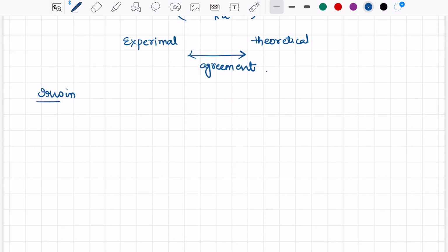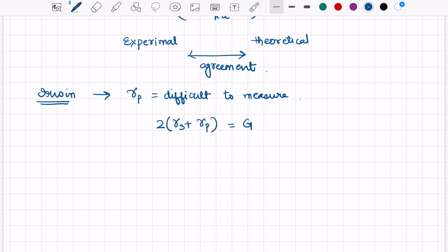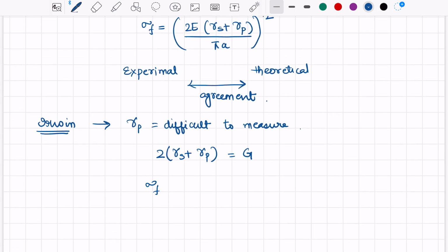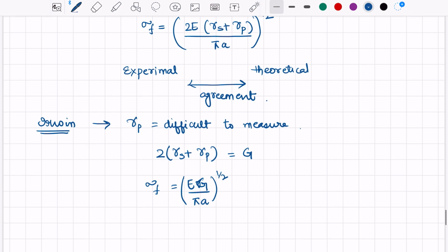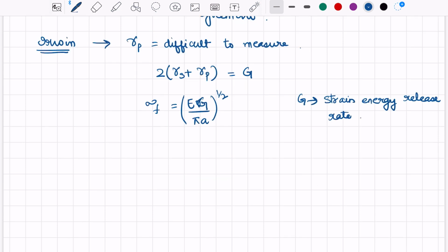Irwin then suggested that gamma p is difficult to measure, hence he replaced 2 multiplied by (gamma s plus gamma p) with G, and he gave the formula (EG / pi a) to the power half. And here G is the strain energy release rate, that is the energy released per unit increase in crack length, or we can say crack extension force. We will see details of each theory in our upcoming videos.